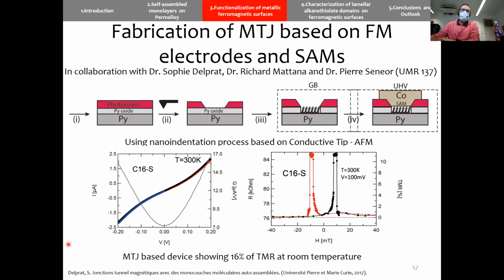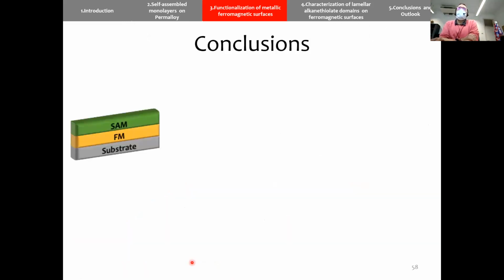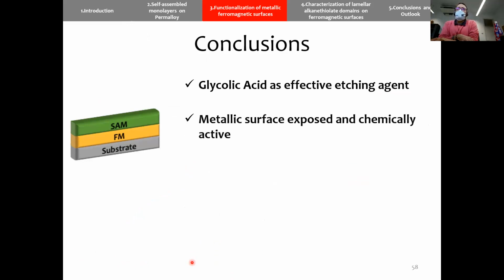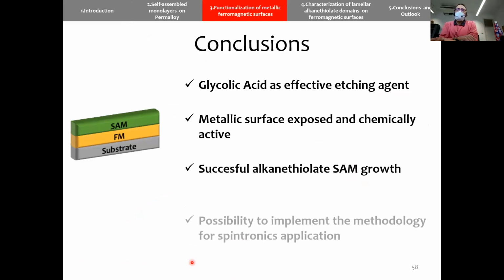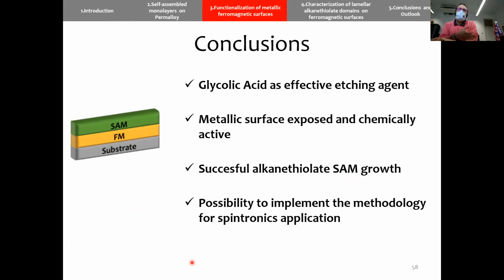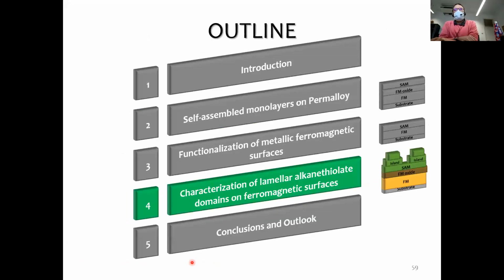So this was done in collaboration with Sophie Delprat, and she showed this nice result in her thesis. So to conclude this part, we have observed that glycolic acid is an effective etching agent. We can expose the surface, and this surface is chemically active. The alkanethiolate SAM is grown, and we can implement it for spintronic applications.